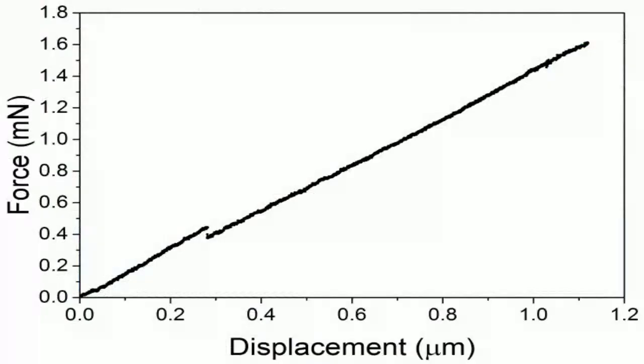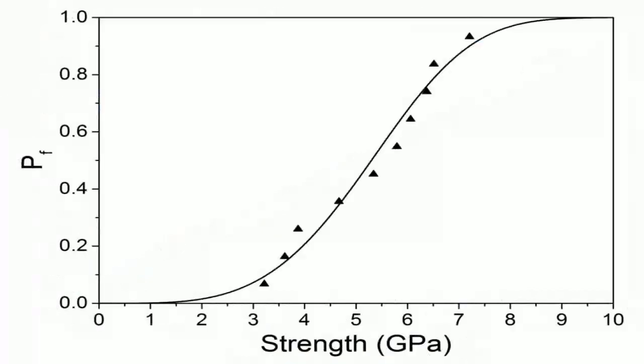Importantly, it lets you measure something called R-curve behavior, where the material's resistance to the crack growing actually increases as the crack gets longer. This is a hallmark of tough materials with extrinsic toughening mechanisms like bridging. The longer the crack, the bigger the bridge zone behind it, the harder it is to push it further.